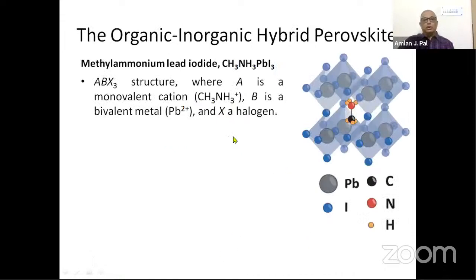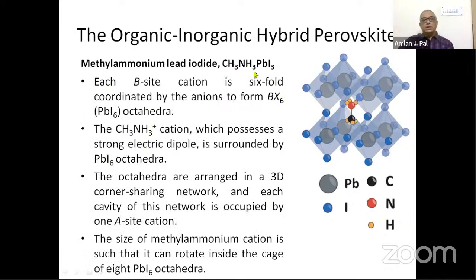So how does the structure of this organic inorganic hybrid halide perovskite, the ABX3 structure or methyl ammonium lead iodide, look? We have this organic component, methyl ammonium, which is a monovalent cation, which sits at the center. Each B site, that is the lead site, is 6-fold coordinated with the halogen. So I have BX6 octahedra, and they are formed like this. There is a kind of cage in this cubic structure, and in this cage I have the methyl ammonium cation sitting. Interestingly, the size of the cage is just good enough to hold this methyl ammonium cation.